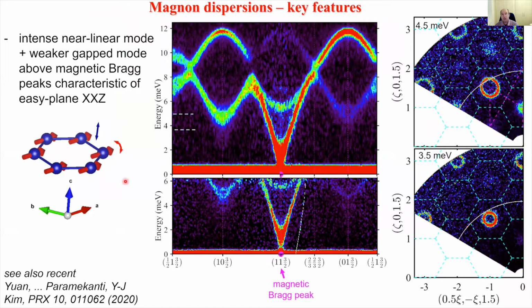So here's a picture of the inelastic neutron scattering measurements. So here is the spectrum as a function of energy vertically and momentum in plane horizontally. And the dominant response here is a very strong linearly dependent dispersive mode that's soft, close to the magnetic Bragg peak position. And this is characteristic of systems that have a strong easy plane anisotropy, where the spin fluctuates very easily in the plane. That's the dominant interaction, where there could also be a gapped excitation out to the plane.